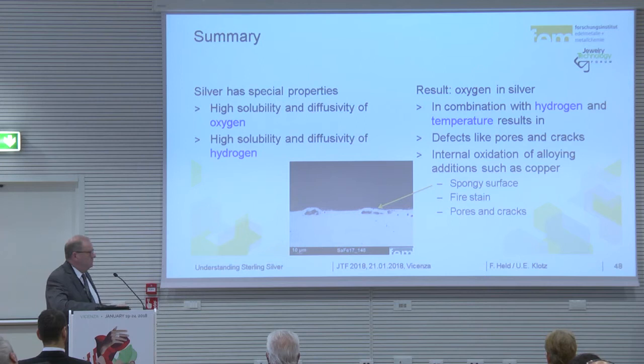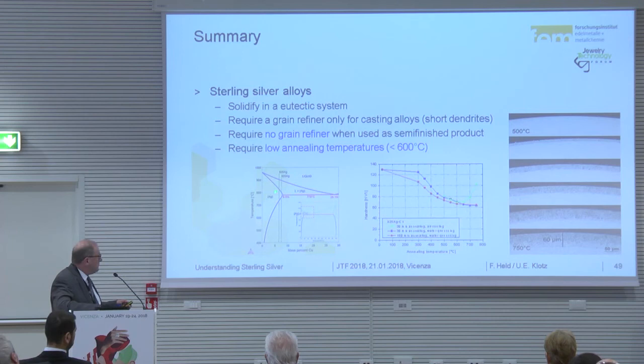And here again, sterling silver. Here the range of our alloys, here hardness, here oxidation. So if not necessary, make the whole annealing and working at temperature below 600 degrees, you have no oxidation, but you have soft material, you can work with it. If you go to higher temperature and you have a bad atmosphere, you get the oxidation you have to remove. It could be you have a self-hardening, which is also not very good if you have to work longer.